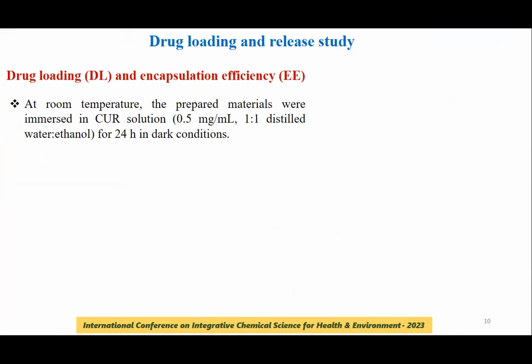Drug loading and release efficiency. The drug is loaded into both the hydrogel and its nanocomposite by the swelling equilibrium method, where at room temperature the prepared materials were immersed in a drug solution with a concentration of 0.5 mg per ml in 1:1 distilled water and ethanol for 24 hours in the dark. 24 hours is selected because it is near the time where the material reaches equilibrium, and the dark condition is to avoid degradation of the drug.